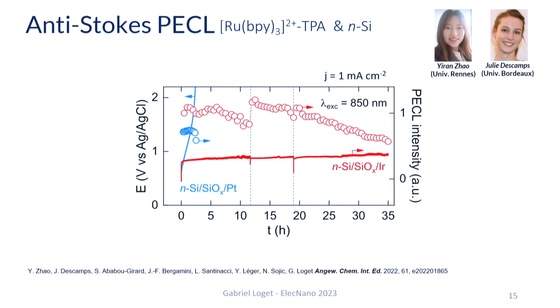So we see that for a platinum protection layer, it works for a couple of hours. So we have a stable PECL emission, but we see that the potential of the electrode is drastically increasing over time, which means that the interfacial resistance is increasing. The electrode is actually not stable.